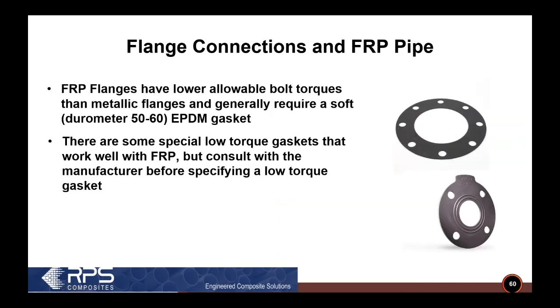When it comes to gaskets, really you'd like to use a soft EPDM gasket with FRP flanges. There are low torque gaskets you can get. You can see this one has the sealing rings built into it. You should really contact the FRP manufacturer before you use anything other than a flat EPDM gasket, because sometimes you have to make adjustments in the FRP flange face to match the gasket style you're using.